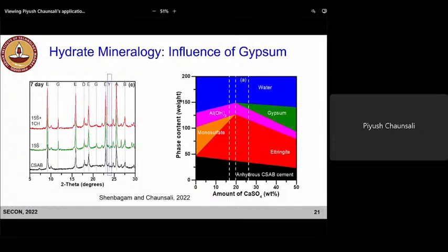For hydrate mineralogy, X-ray diffraction can be used to look at the phases formed during the hydration of CSAB cement, and you see here a significant amount of ettringite, the crystalline phase responsible for expansion, right? As we increase the amount of gypsum, we see an increase in the amount of ettringite. Also, notice the Y is the ye'elimite peak, around 23.4 or 23.5 degrees 2 theta. We can monitor how quickly this is disappearing. Basically, this is a phase which is hydrating, right? By monitoring its amount with time, we can also estimate the degree of hydration.